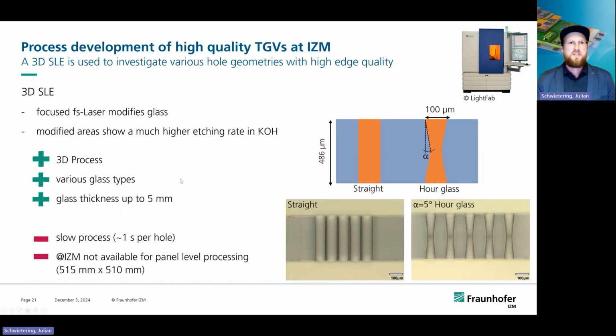And that's why we are using a 3D SLE system to investigate various hole geometries, and all this with really high edge quality. We are using a 3D system with a focused laser that modifies the glass. After the modification, the modified areas show a much higher etching rate in KOH. So we can etch this, and after this, we have the structured glass.